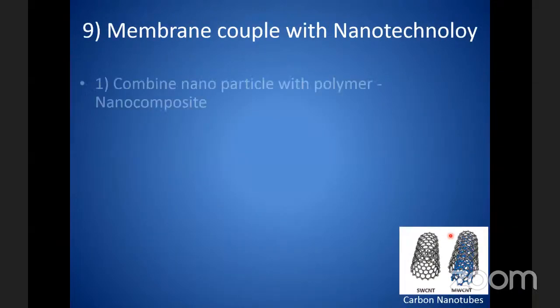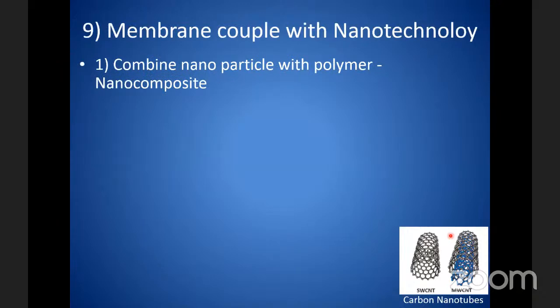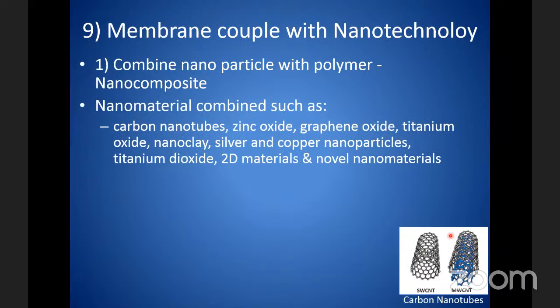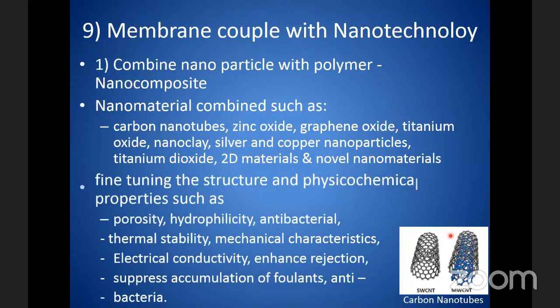So membrane coupled with nanotechnology. Normally, now the most popular one is to combine nanoparticle with polymer. So it's called nanocomposite. Right. So this nanomaterial combined, such as carbon nanotube, zinc oxide, graphene oxide, titanium dioxide, and so on, silver, copper, 2D material or novel ones. So you fine-tune the structure of the membrane and physiochemical properties such as porosity, hydrophilicity, antibacterial, thermal stability, mechanical characteristics, electrical conductivity. So with some nanomaterial in the membrane, you can use electricity to induce it so that it will remove the foulant or cause some reaction on the foulant.